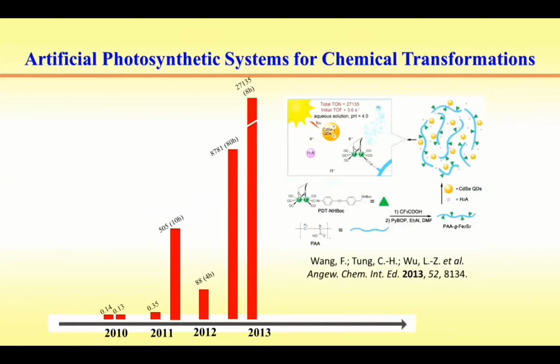Nevertheless, the efficiency of the hydrogen evolution is less than that of the natural hydrogenases, which can produce 6,000 to 9,000 molecules of hydrogen per active site per second. To address this point, we introduced the first set of polymer-based hydrogenase mimics for hydrogen generation. The system shows exceptional turnover numbers, that is 27,135, and the turnover frequency equals 3.6 per second per active site.